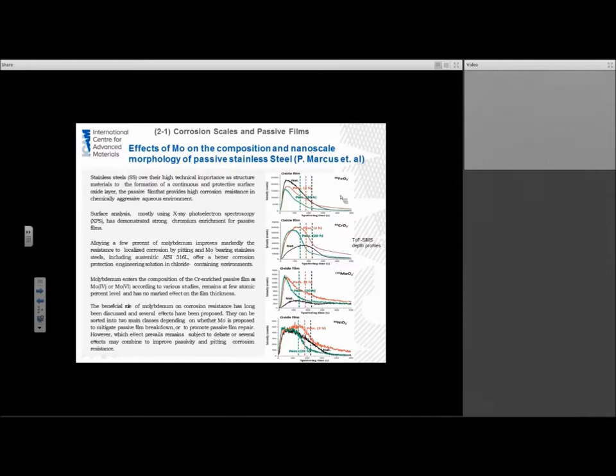He's looked at iron oxide ions, chromium oxide ions, and the molybdenum oxide ions. If we take a look at molybdenum, we see that the molybdenum actually sits at the near surface to oxide interface in the naturally forming oxide. As you age the material, this presence shifts and enriches toward the outer oxide in both the two-hour and the 20-hour aging treatment. If we take a look at where the chromium and the iron sit, we see that the chromium is in the near oxide, whereas the iron is always going to be in the far outside oxide.